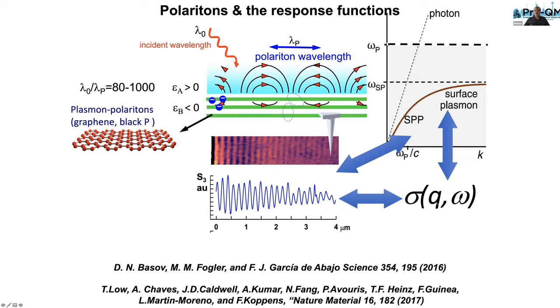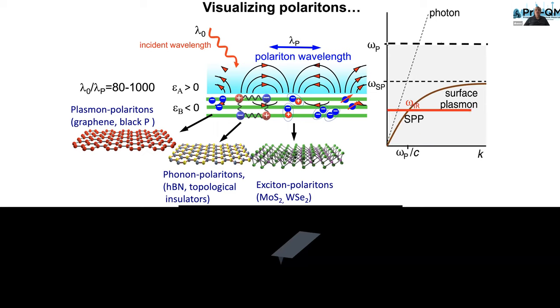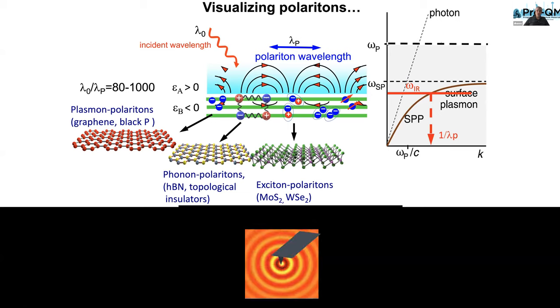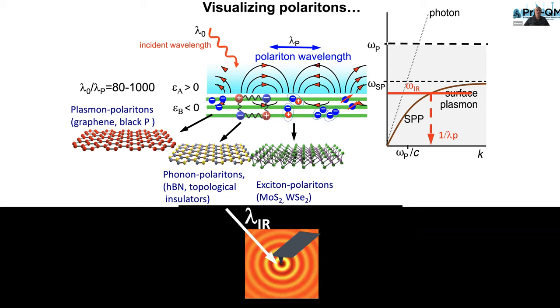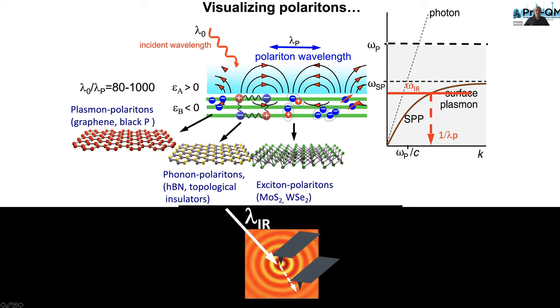From the images, you can obtain the response function through determining the dispersion, and that sets the stage for quantitative inferences that you may want to extract about your medium, specifically about response functions that are not only frequency but also momentum dependent. So this is how polaritonic imaging works. With the tip, you select the range of the frequency of your laser such that it goes into the curved region of the dispersion, and then the tip of your near field apparatus acts as a launcher of polaritonic waves that travel on the surface. So the purpose of the tip is to convert free space light into high momentum modes that are confined to the surface. And you can catch this polaritonic wave with another tip if you wish.